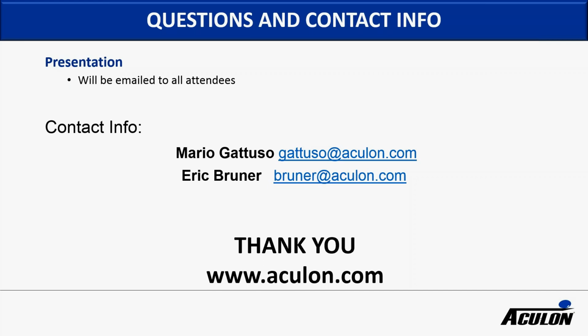Great, thank you, Eric. Next question that's come through is, is it possible to apply a powder coating type finish over your coatings? For our repellent treatments, the action of making the surface repellent to liquid also acts as essentially a mold release, reducing the surface energy. So you could attempt to apply a powder coating, but the adhesion to the surface is going to be compromised. If that's not an issue, you could potentially apply it, but you may have delamination or adhesion issues. With the hydrophilics, I'm not quite sure. Eric, do you have any thought on whether they could apply a powder coating over the hydrophilics?